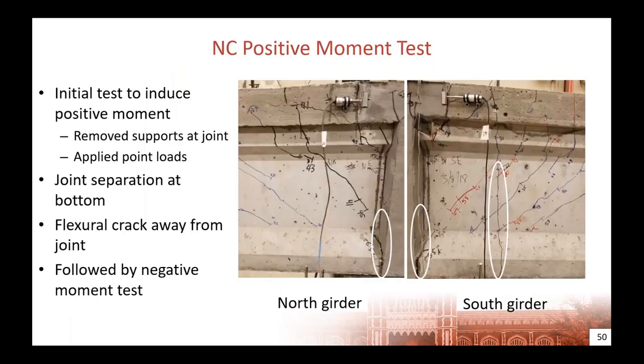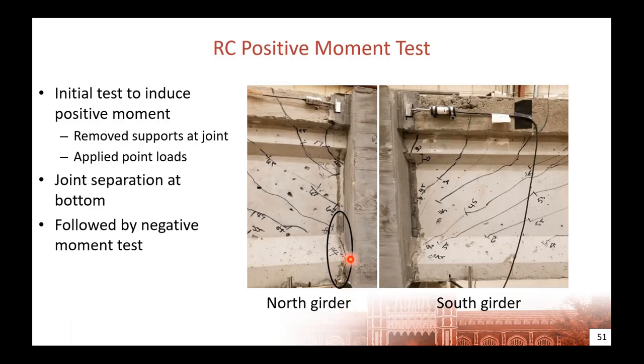When we took out that middle support and tested for positive moment for the new construction, the types of damage that we saw were cracks at the joint interface on either side, and then also saw flexural cracks out away from that interface in the section where we didn't have the full pre-stress. For the retrofit construction, we only saw that damage at the interface. We didn't see it out into the beam.